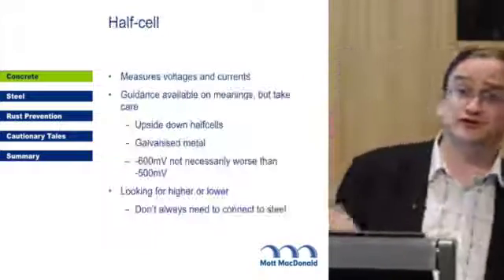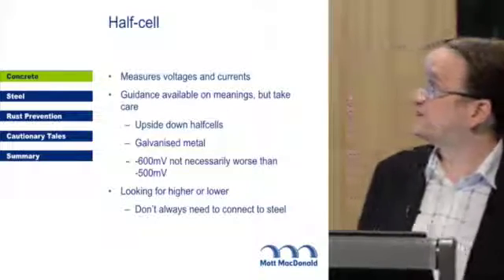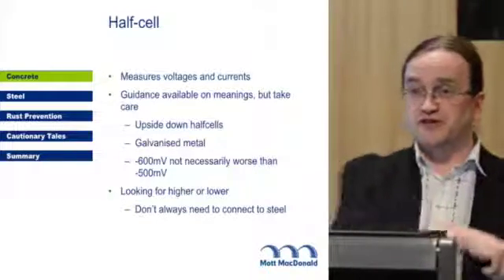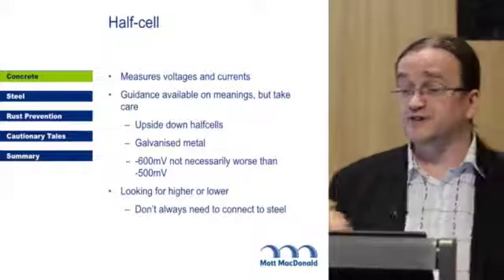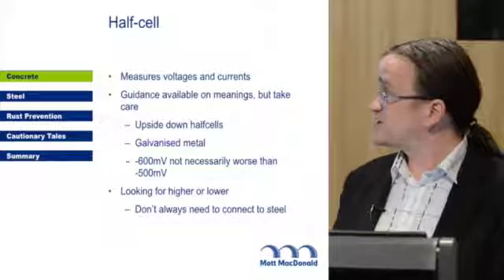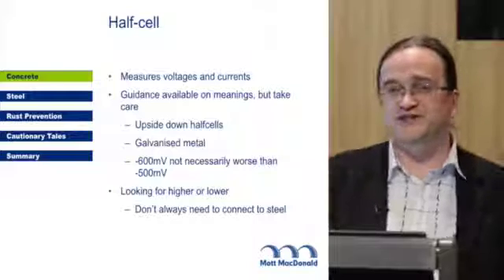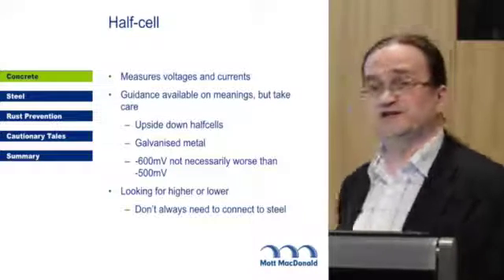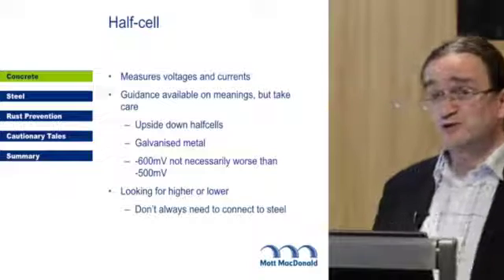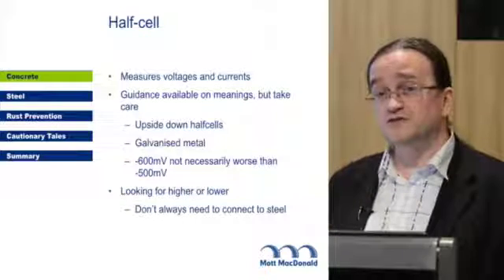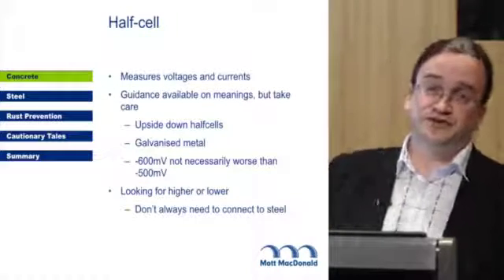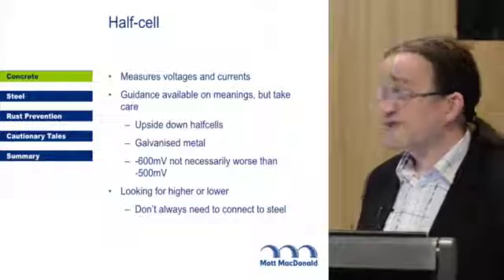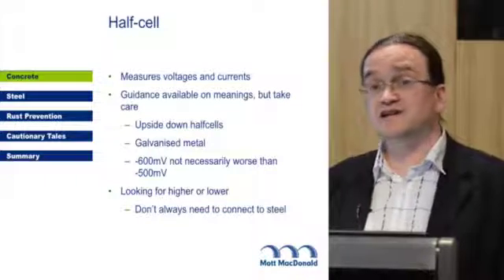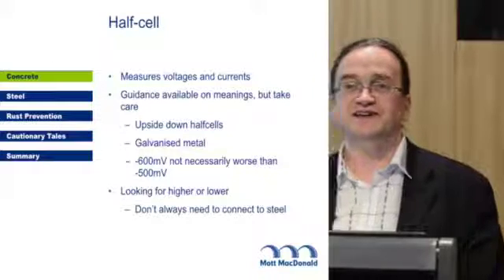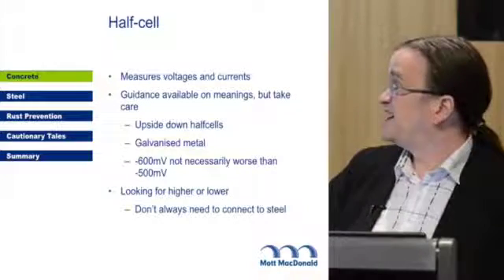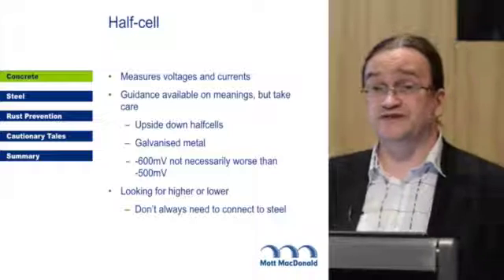Half cell potential, also known as reference electrodes, we measure the voltages. And because we know the voltages that are associated with corroding steel, we can work out where it's corroding. There is guidance on the readings, but they were based on 6 bridge decks in Florida and then universally adopted across the entire world. And they work most of the time, but some half cells don't work upside down. So if you're doing a soffit, make sure you've got one that works that way up. If you've got galvanised metal, it'll be kind of -900 because that's what zinc is. And because more negative indicates an anode, people get awfully excited when you get negative readings.